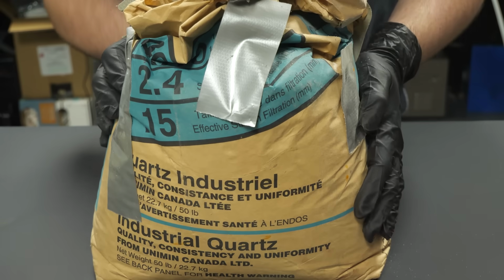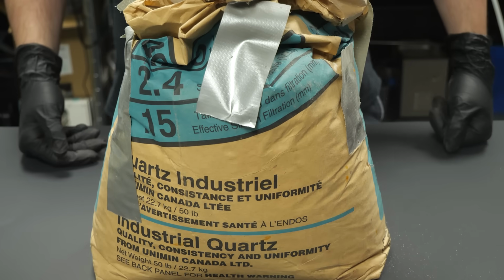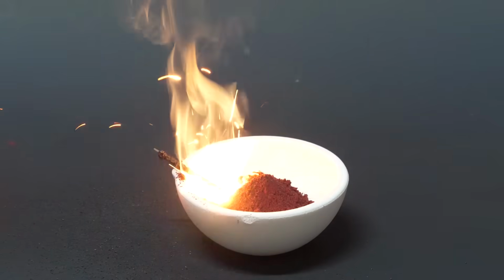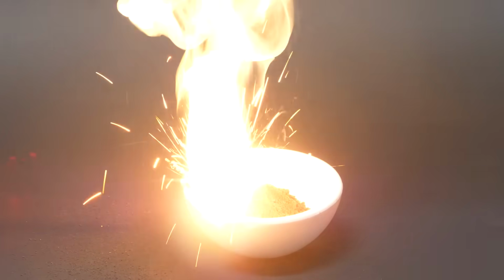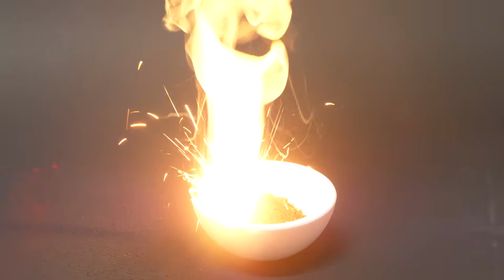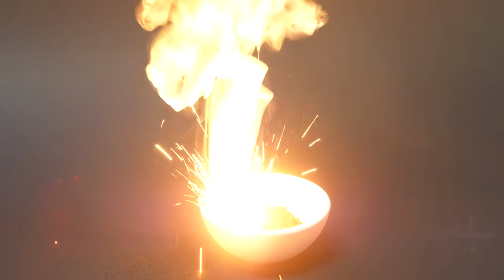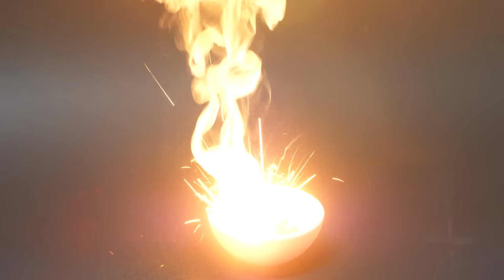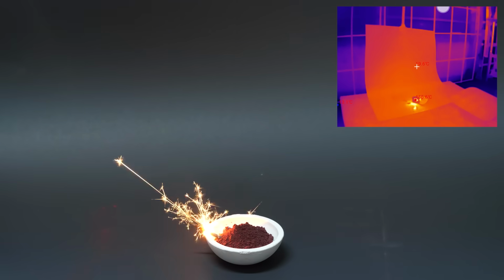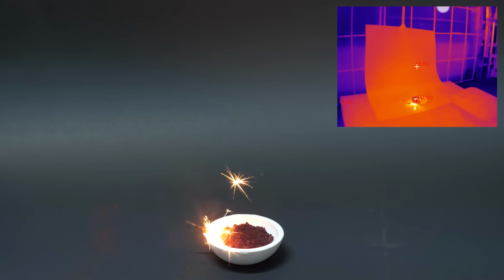The solution we found was to use quartz sand mixed into the thermite. When you add the right amount, it still burns really well, but it doesn't spray stuff everywhere. While the silica can burn in the reaction, any that doesn't just melts and acts as a sticky glue to hold the burning mass together. To figure out the right amount, we tested three different concentrations of silica.